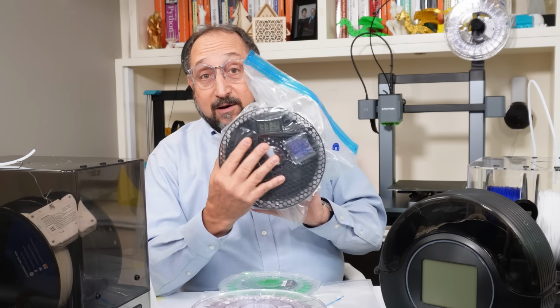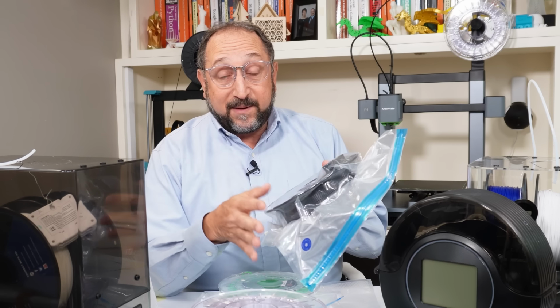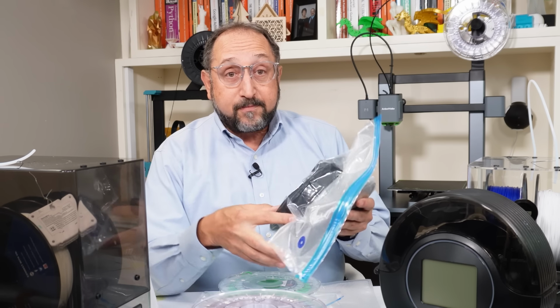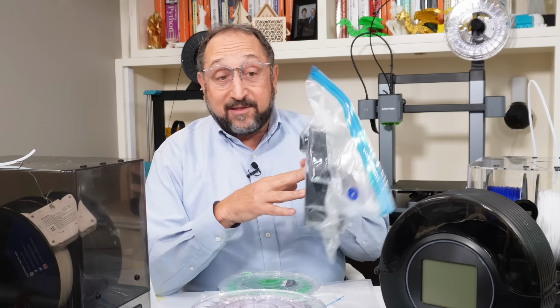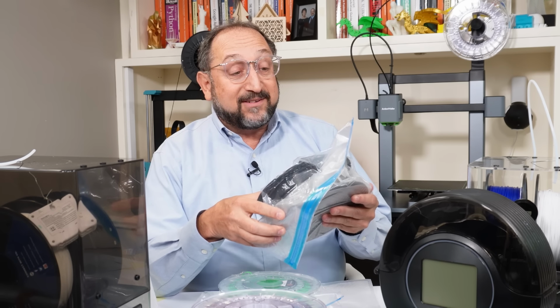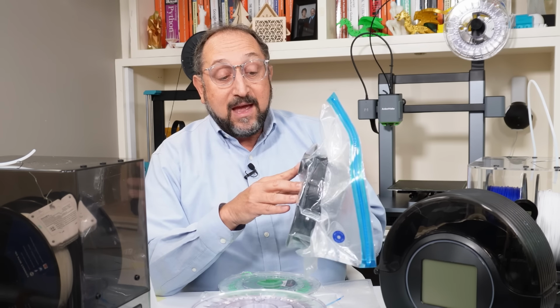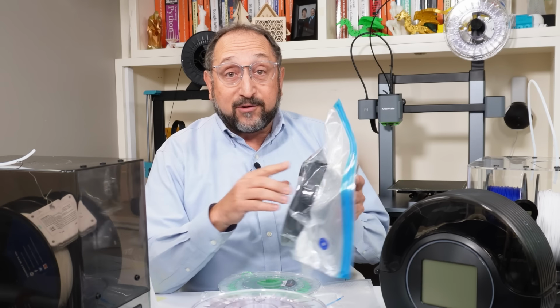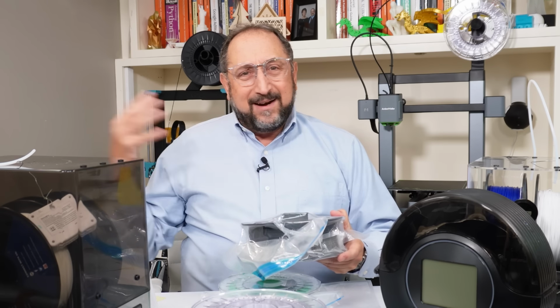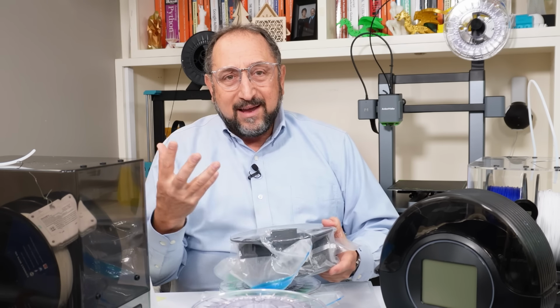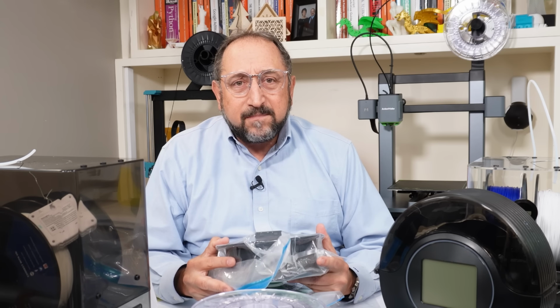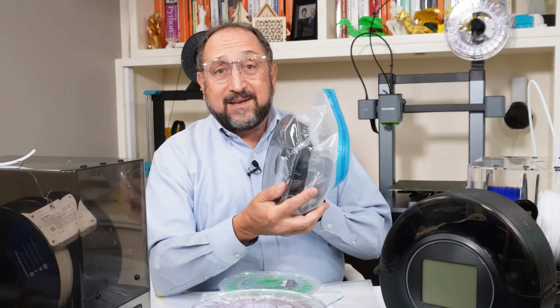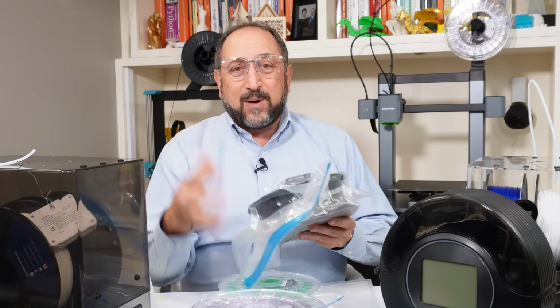That will tell you the humidity. Now, they're not absolutely accurate, but they'll give you the right ballpark. So in this particular case, this is PETG. This happens to be Prusa PETG. And it says the temperature inside this bag is 71.6 degrees Fahrenheit, and the humidity is 33%. Now, I can tell you the humidity in the air here is about 55%. So that says that this filament is drier than the surrounding air.